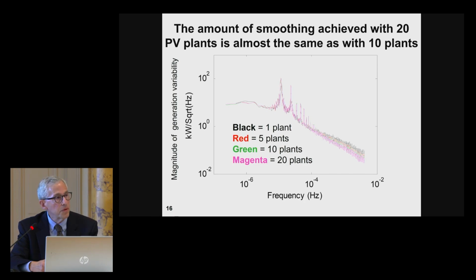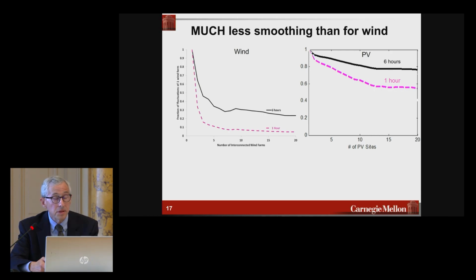And let's compare the smoothing of PV to that of wind. And what you see on the left is the same curves I showed you for wind. And on the same scale on the right is PV. Instead of smoothing out 95% of the fluctuations at the asymptote with 20 plants, you smooth out about half. Instead of smoothing out 75% at 6 hours, you smooth maybe 25%. So the smoothing of PV, if you're feeding something like the electrolyzer or the ammonia plant that we were talking about earlier, is going to require much more compensation.